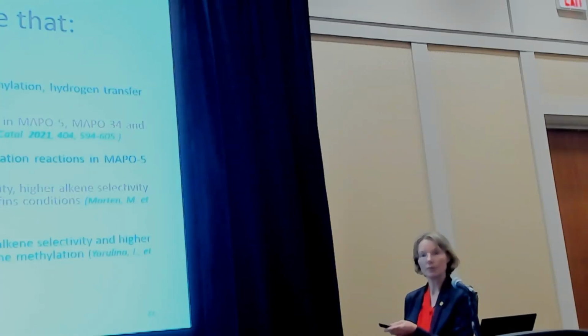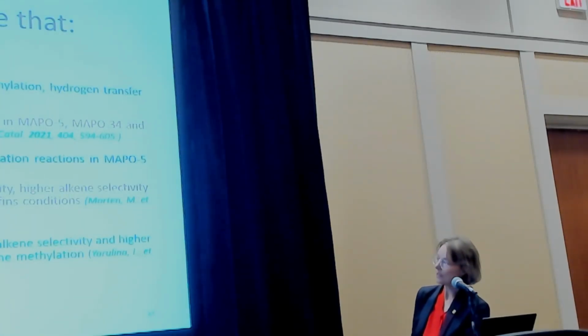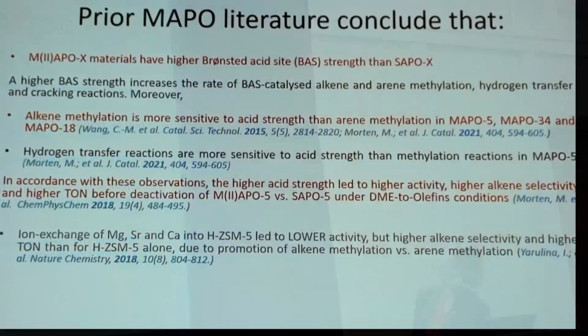Yes, we have one other point which I also think is relevant here, and that is that it has previously been shown from Luleå's group, Hedlund and co-workers, that if you ion exchange these alkaline earth metals into silicalite-1, you see much of the same effect that we see with the heteroatoms incorporated in the lattice. That means that you have, of course, lower activity because they are covering some of the Brønsted acid sites, but you have a higher alkene selectivity and higher turnover number than you have for silicalite-1 alone. So they are acting as Lewis acid sites also in this structure.